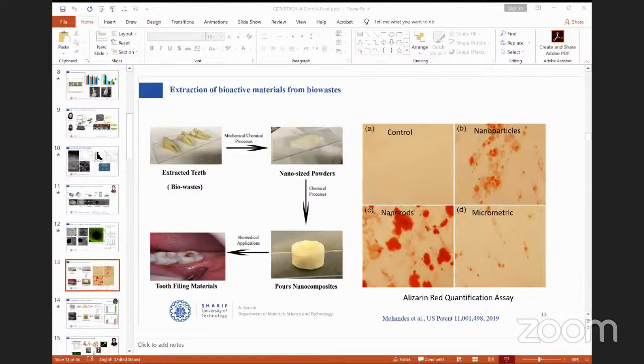There are some commercially available particles, but we found that it's very interesting if we could develop hydroxyapatite from natural sources. For example, we can use the bone or teeth. We have especially developed a procedure to transform teeth to hydroxyapatite nanoparticles and nanorods. And it's subject to a US patent in 2019. And on the left-hand side, you see the Alizarin red quantification assay.